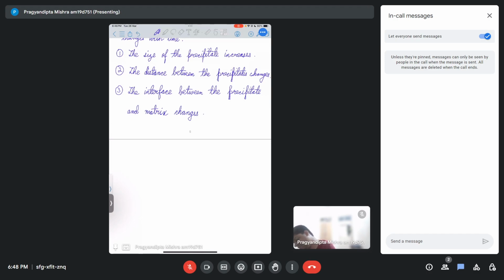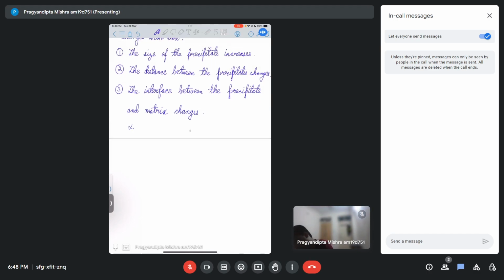So what are the steps or sequence by which this precipitation will happen during aging? Essentially, first you will have alpha phase, which is the supersaturated solution. Now that will transform into something known as GP zones. These are particles present within the matrix that do not act like precipitate, but create some sort of weird interface between the matrix and whatever phase the GP zone is holding. They are like an interface between the precipitate and the supersaturated solution, which will result in the formation of the first type of precipitate, theta double prime, then theta prime, and then theta.